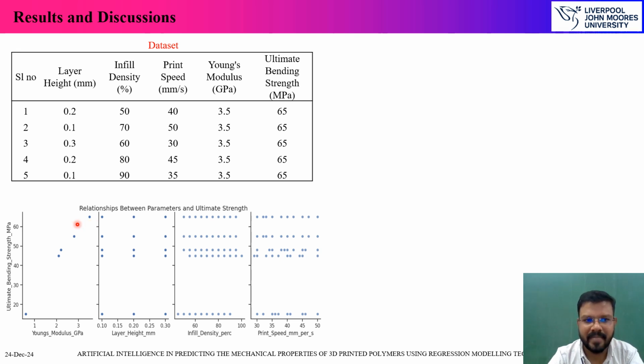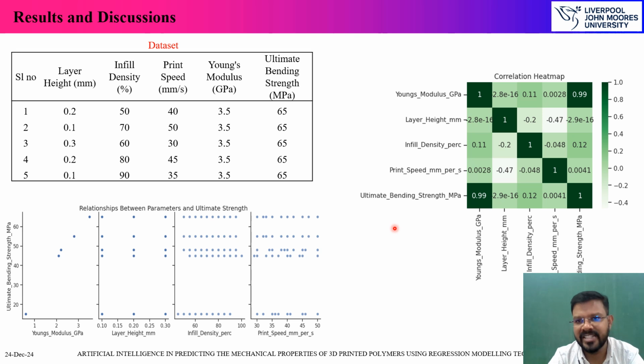65 megapascals. So from this particular plot we could say that the value of ultimate bending strength is directly proportional to the Young's modulus value. And to substantiate that, we could also see the same in the correlation heat map, which has the second highest value of 0.99, that is Young's modulus measured along with the ultimate bending strength. So this is under the high correlation.